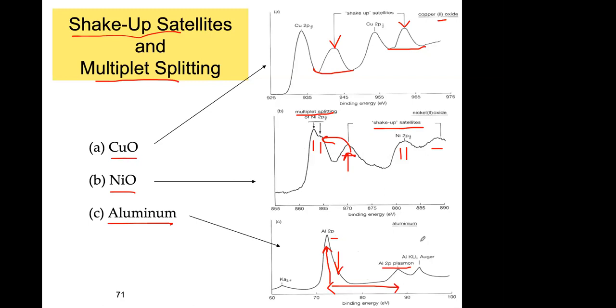In addition to that, you have an Auger line, KLL, that I'll explain tomorrow. It's an Auger line. And in addition, there is a satellite peak from the X-ray source, because this photon, K alpha 3 and 4, excited the 2p electron. But since the binding energy is calculated with the K alpha 1 and 2, you're not calculating properly the binding energy. So this other peak here is a satellite due to the X-ray source. If you have a monochromator, you won't see this. But if you have a polychromatic source, a dual anode source, you will see satellites now and then because of the X-ray source. So these are the things that you can see.